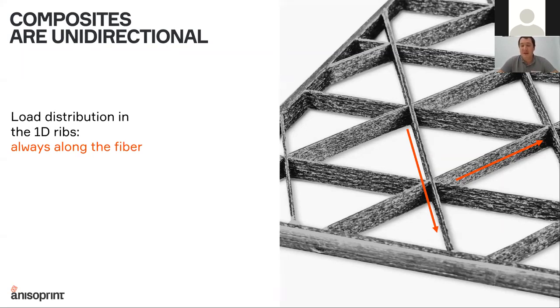But if we have a lattice structure that consists of unidirectional or 1D ribs, the stresses in every rib, in every one-dimensional structure, are also one-dimensional. So the rib will not work in the transverse direction. It will only work in the longitudinal direction, along the rib. So composite materials, with their anisotropic nature, have a very good fit for lattice structures. In lattice structures, composites only work along the fiber. That's why these types of structures are the best for composites.